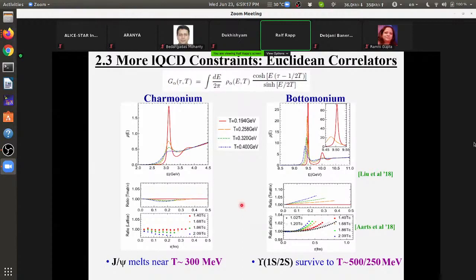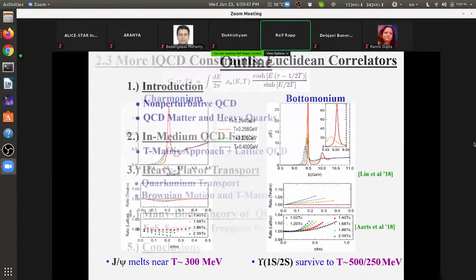So you have some confidence that this rooting of this many-body theory in the lattice data within this potential or T-matrix approach can be made sense of in a way. And maybe I should quote some numbers here. The J/psi in this approach would melt in this calculation at about 300 MeV, so indeed survive into the QGP. The 1s upsilon even deeper, while the 2s would actually dissolve a little earlier. Okay, so